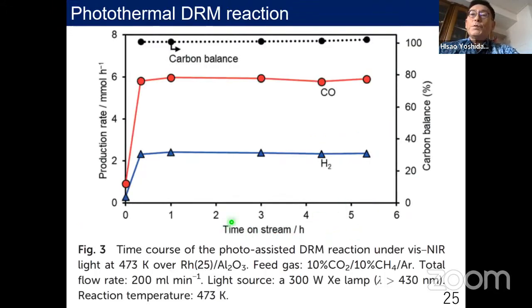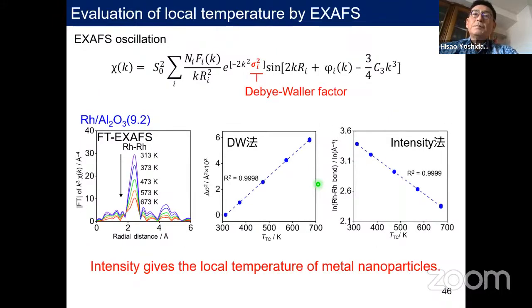Here is the result and the time course of the reaction. We can obtain carbon monoxide and hydrogen as products in the DRM reaction continuously. So we successfully obtained a good system. To know the reaction temperature, we used the EXAFS technique. I would like to show the principle of the EXAFS oscillation here, but it is very difficult, so I will skip the details. However, the Fourier transformed EXAFS gives a clear peak due to the rhodium shells. The intensity depends on the temperature, so we can calculate the temperature from that spectrum change.